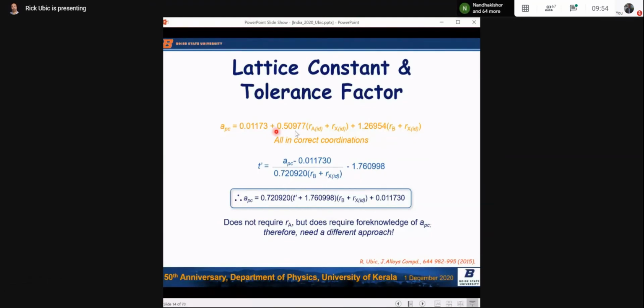So from this equation, we can define the tolerance factor by solving it for the Goldschmidt tolerance factor. But in this case, when we do that, of course, we get this, right? Because we're rearranging this equation. So we get this. So I call this T prime because it doesn't look identical to the Goldschmidt. Why would we recalculate the Goldschmidt tolerance factor? It's a different way of defining the tolerance factor, and it's actually much better at predicting structural effects, which I won't go into too much, but it's another way of calculating the tolerance factor, but it's not Goldschmidt, so I call it T prime.